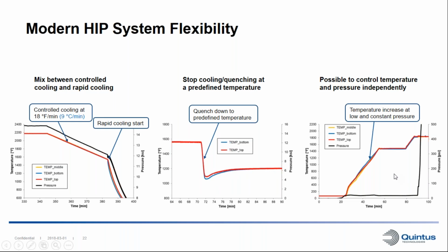On the right here, we can see that we also can control the temperature and pressure independently of each other. In this case, we have a low and constant pressure in the beginning. At the same time, we're increasing the temperature. We have a hold step, increase the temperature again, and when that has reached steady state, we start to increase the pressure to typical HIP pressures.